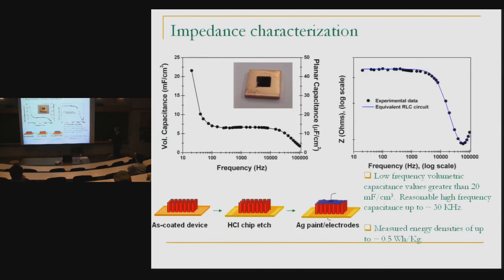Okay, so basically, the way that I do the capacitance measurement is that, of course, these are on a conductive substrate, so I have one probe on the bottom of the system. And then you have the dielectric coating, which is on top of the whole structure. And then what I do is I go through with a very dilute HCl and basically etch away the conductive material in this region, so I don't short the device by coating it from the bottom. And then you're measuring the capacitance from here, which is a conductive region, through the dielectric, which goes through this whole nanotube material, and then I put a little bit of silver paint on top in order to make the top contact. And of course the silver paint is connected electrically to the aluminum doped zinc oxide. And so you're probing the capacitance of the whole structure as electrons, or holes, can go into the aluminum doped zinc oxide as well as to the top contact.